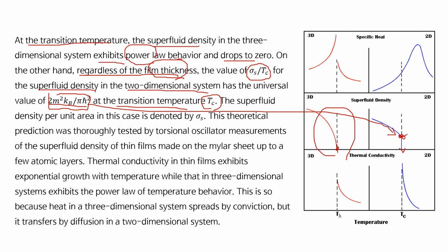The superfluid density per unit area in this case is denoted by sigma s. This sigma s is the superfluid density per unit area. This theoretical prediction was thoroughly tested by torsional oscillator measurements of the superfluid density of thin films made on the mylar sheet up to a few atomic layers.